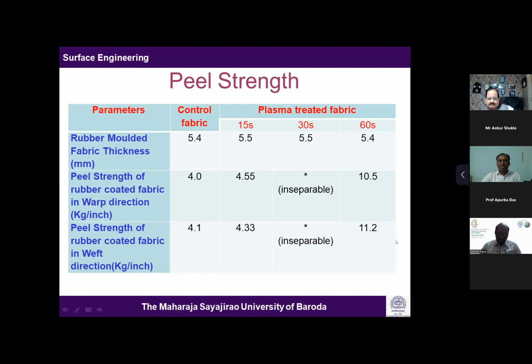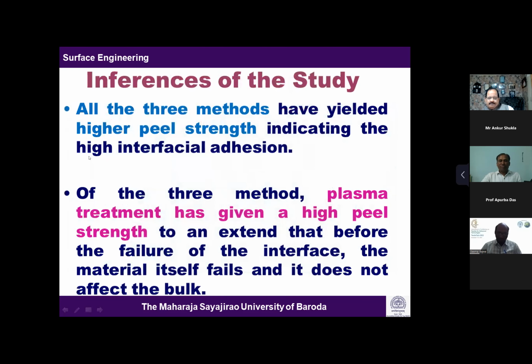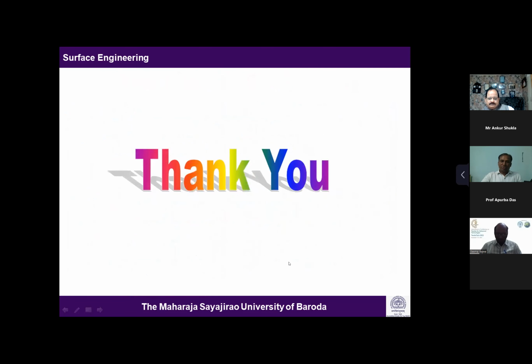Of course, in all three techniques, the inference is that all three methods have yielded higher peel strength, indicating higher interfacial adhesion, and that is, as we discussed, because of the increase in the surface roughness. Of the three methods, plasma treatment has given such a high peel strength that before failure of the interface, the material itself fails, and it does not affect the bulk compared to the other techniques. So thank you, and this is what I wanted to share in this forum.